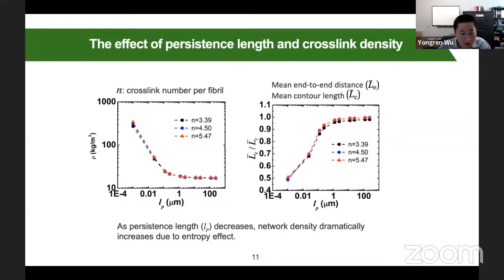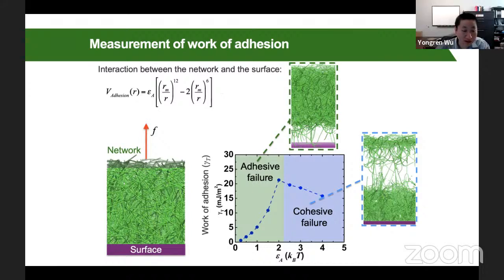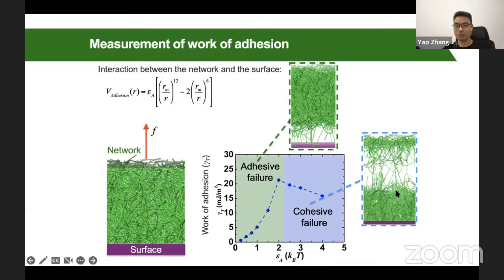And you also simulated the failure pattern, right? Do you mind elaborating a little more on how you define the failure criteria for this network? You mean the failure criteria? Yes. It looks like we can see this kind of failure pattern, so how do you make it work? Just look at the simulation: whether the majority of the network can detach from the surface. If the majority of the network detaches from the surface, it means that cohesive failure will not happen. In this case, you can see that the majority of the network in contact with the surface just stays there and doesn't move.